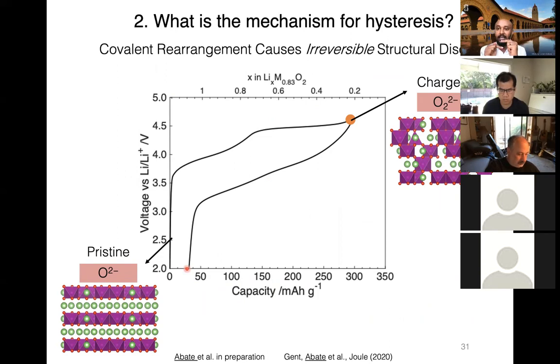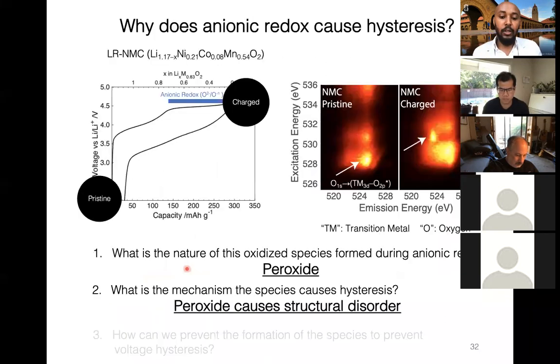Because of this path dependency, we have what's called the voltage hysteresis that has been shown in the past few slides. So this explains why we have hysteresis and why we have path dependency. This is because of the cationic disorder and the peroxide forming this configuration that will affect the pathway moving from left to right and right to left. So this answers the second question, that the mechanism behind the hysteresis is that the peroxide formation coupled with cationic disorder is causing material instability that causes hysteresis.